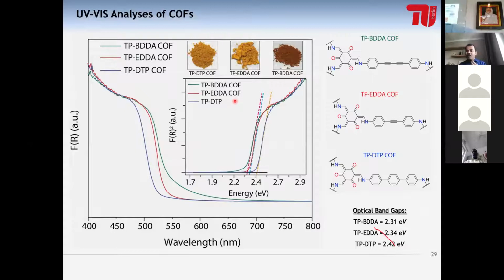And to do that, we did the solid-state UV analysis, and now you can see that the COF TP-BDDA has the absorption. This green line represents the absorption of this particular BDDA COF, and now we can exactly see that the COF having diacetylene moiety in its backbone shows the absorption more in the visible region. So it is becoming more and more interesting now, because you just put one moiety inside and you start absorbing more in the visible region, as we are expecting, because it is really important for us to get the material absorbing in the visible region to achieve the photocatalytic hydrogen generation in just normal sunlight.